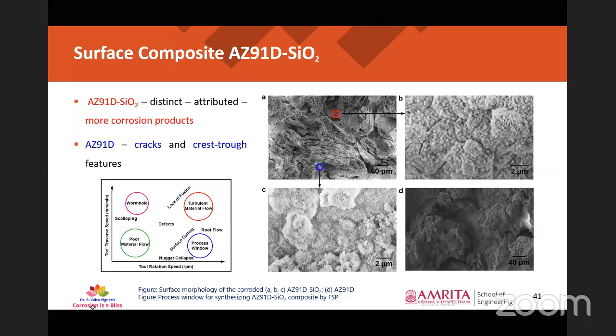And added to that, the conventional material AZ91D had very crest and trough features, and the features for corrosion products are much fewer compared to the composite that we have developed. So from this, we could conclude that AZ91D silica composite is one of the effective materials for biodegradable implant applications. So here is the process window for fabricating composites.